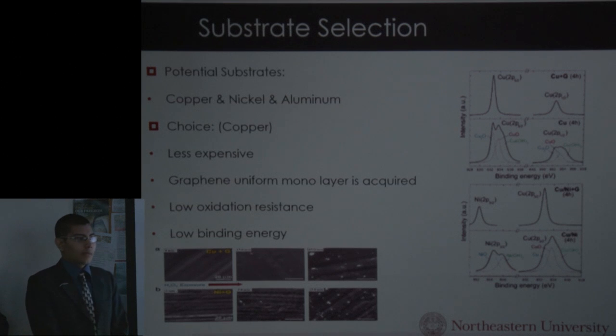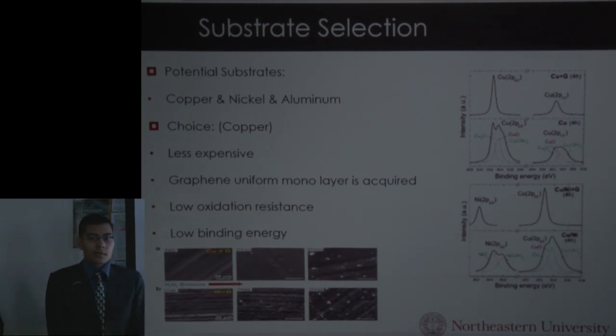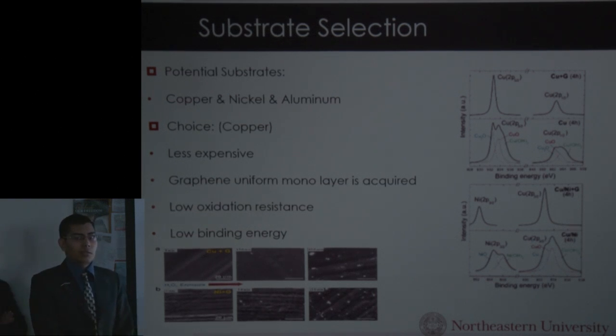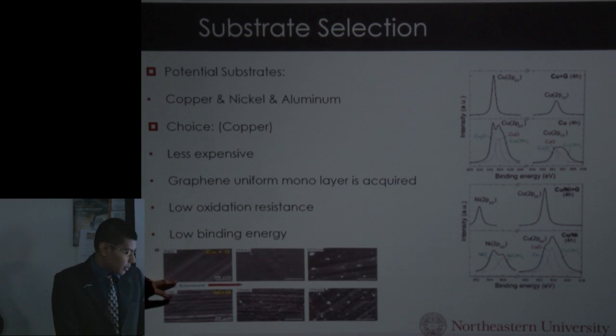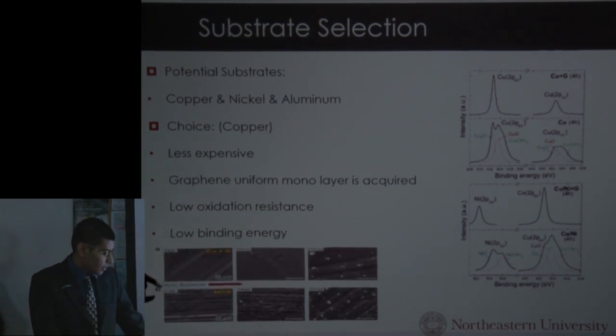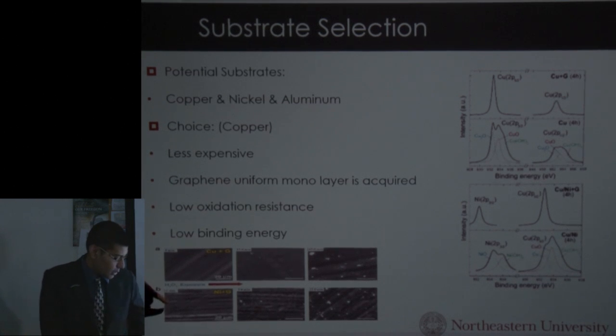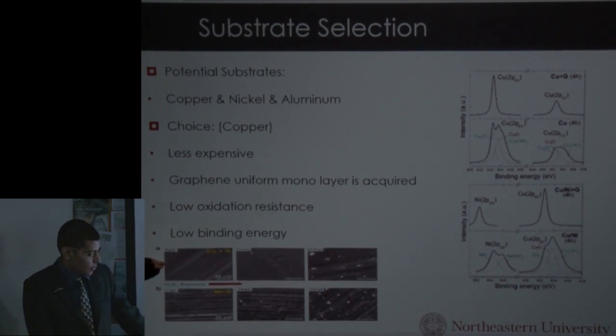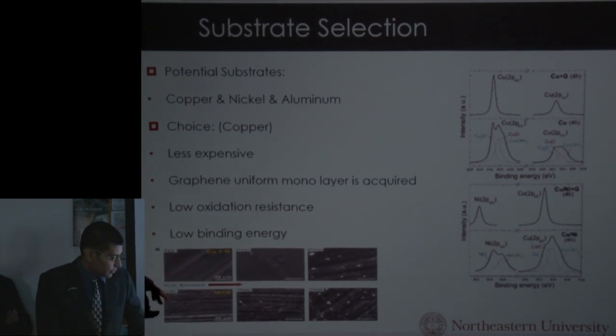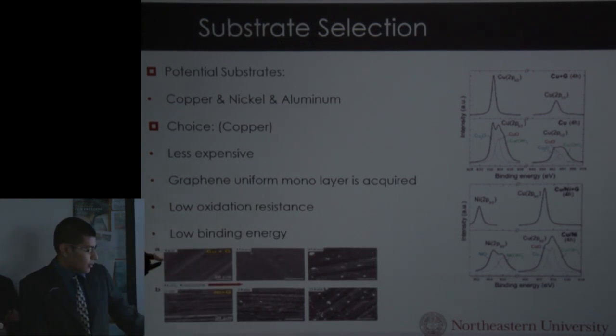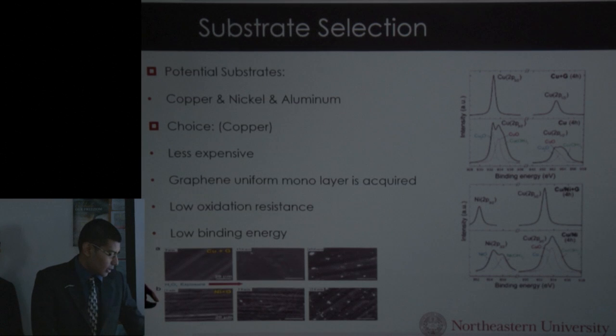Also, copper and graphene composite form uniform and monolayer, and it has a low oxidation resistance and low binding energy. Our final product is not copper and graphene, but graphene in silicon dioxide, so we need a substrate that's easy to remove. As you can see in the microscopic view, we have two different sheets. One is copper graphene and the other is nickel graphene. Copper graphene is more smooth and monolayer, whereas nickel graphene is multi-layer and uniform. Hence, it's easier to extract copper out from graphene rather than nickel.